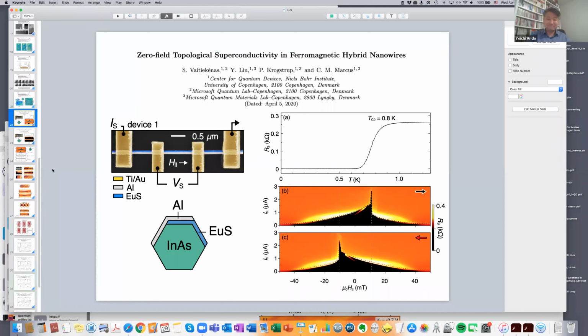Now, wait, let me add, Yoichi, one more thing, which is that unlike Tedrow-Meservey or unlike the Giazzotto experiments, we're tunneling into the semiconductor, which means that there's also spin orbit coupling that's playing an important role. That can also mix the spin bands. So I think that both the spin orbit of the semiconductor, which is where the tunneling is occurring, and the roughness of the interface that gives an effective spin flip scattering are both at play, and I don't know the ratio between the two. Okay, alles klar, danke.